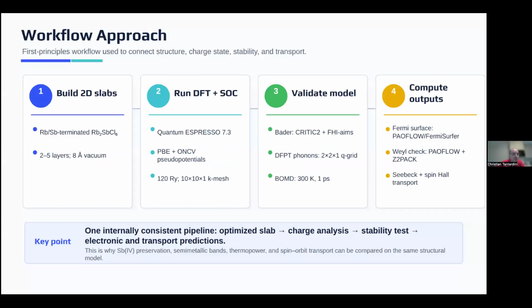So to do this, there is a workflow approach that we have used. Specifically, we worked on building the 2D slabs, rubidium terminated and antimony terminated, from the conventional cell of the rubidium 2 antimony chlorine 6, from 2 to 5 layers, making a necessary vacuum. We run a DFT plus spin-orbit coupling.